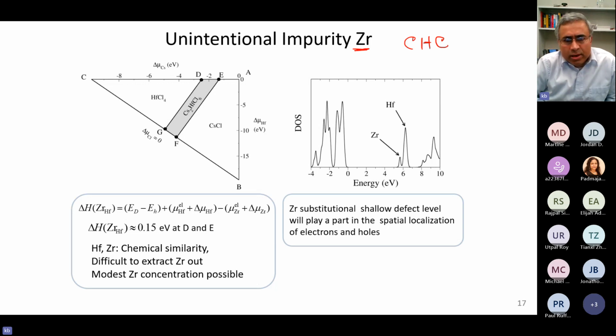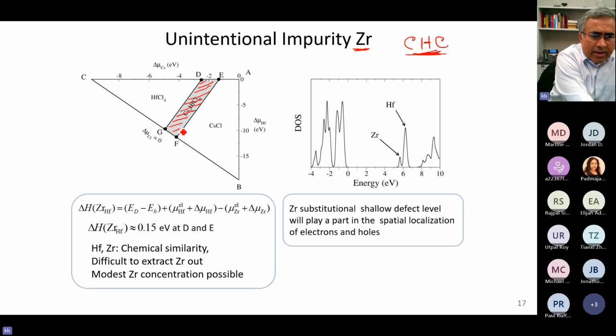So we looked at zirconium. When we do calculations, we can do them under perfect circumstances. When we build up our crystal, we can build a perfect CHC crystal with no zirconium at all. But that's not the practical case. Experimentalists will encounter zirconium, so that's why we looked at the effects of zirconium. What you see here, we call a chemical potential diagram. I'll not go into too much detail, but its importance is that it gives you the stability region, not a phase diagram in the experimentalist's sense, of cesium hafnium chloride with respect to other competing phases, for example, hafnium chloride or cesium chloride and so on.